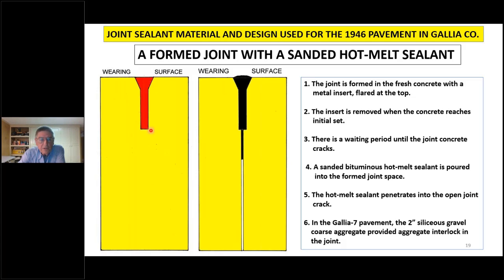That was put in, of course, at the time of pavement construction. It was removed when the concrete received initial set. They waited until the concrete cracked, and then they poured a sanded bituminous hot melt into the formed joint space, which obviously filled the space that they had created. And also, in the sample that we looked at, it went down into the crack itself. And those were still there at the time we did, at least in the core that we took.